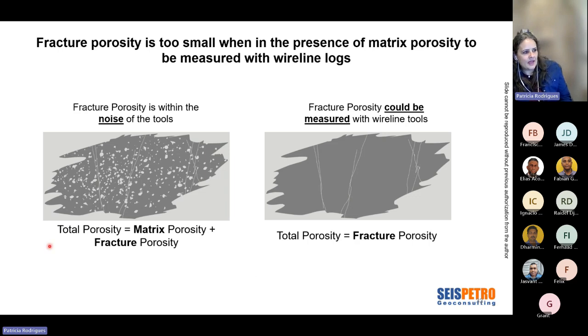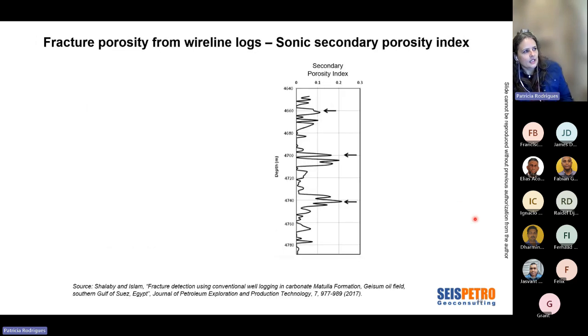So, as I said, in many instances, especially when you have a lot of matrix porosity, the fracture porosity really becomes some kind of noise. When you are measuring the porosity from your neutron density logs, you're measuring both the matrix and the fracture porosity together. But the fracture porosity is so small that it's really hard to differentiate between them. When you're in systems where there is no matrix porosity at all, then whatever porosity you are measuring with your neutron density is actually your fracture porosity. That's kind of straightforward.